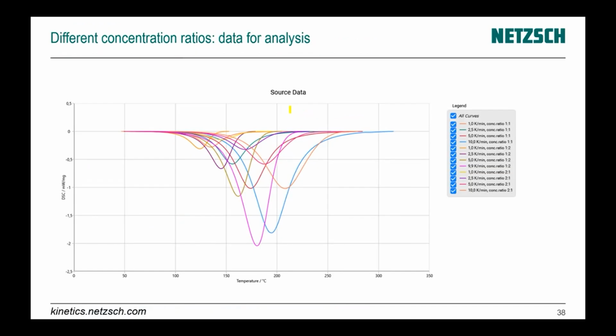Our next example is really new. Here we can find how the reaction rate, the curing rate, depends on different concentration ratios. Here we have data for our analysis. We have 3 different ratios, 1:1, 1:2, and 2:1. It's a ratio of epoxy to aniline. And for each ratio, the measurements are done for 1, 2.5, 5, and 10K per minute.